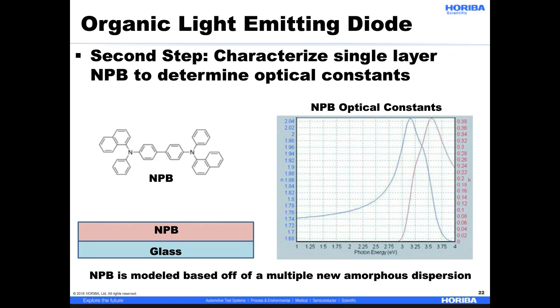The second step here would be to characterize the single layer NPB to determine its optical constants. Again, this is a single layer of NPB on glass, and you can see the resulting optical constants for NPB. NPB is modeled, again, off of a multiple new amorphous dispersion function.